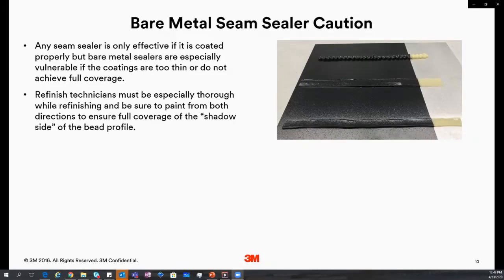So this might end up leading to a conversation that needs to be had more often between the body technician and a paint technician in these areas where they're applying bare metal seam sealers, actually going and having a conversation about saying, hey, you know what, we need to make sure that I have bare metal here. Can we make sure that we get the adequate number of coats applied to this to really provide a good corrosion resistant repair? And those are going to be very important conversations to have within the shop, right?